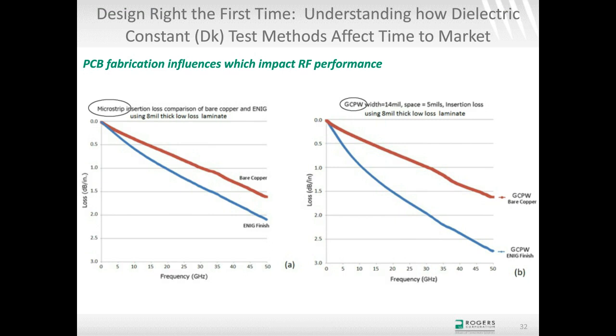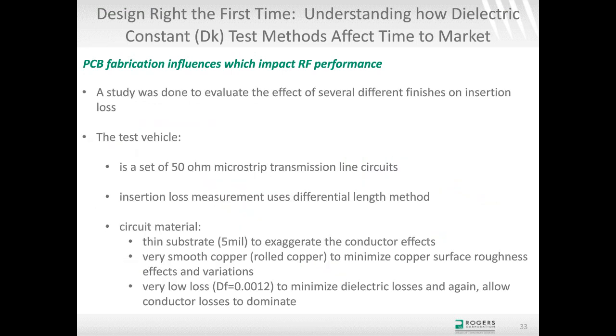So on the left is, all of this is actually using the same material, 8 mil thick RO4003C. On the left are 50 ohm microstrip transmission lines, red curve bare copper, blue curve circuits with e-neg. Difference of losses at 50 gigahertz, about 0.5 dB per inch difference. The chart on the right is same materials again, except now it's 50 ohm ground coplanar waveguide. Difference of bare copper red curve and blue curve e-neg at 50 gigahertz is about 1.2 dB per inch difference, so a pretty big difference. So design really does make a difference when it comes to the issue of final plated finishes and how that affects insertion loss. So let's take a look at something else we did.